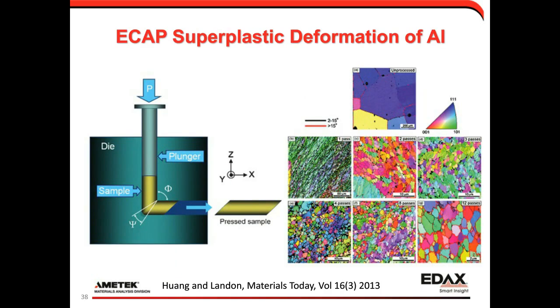And this is just an example here. One of the things research is focused on is using different methods of introducing superplastic deformation to refine and control the grain size. This is what's called equal channel angular pressing or extrusion, where you push a material through a die that takes a strong turn, in this case 90 degrees. Your pressed sample comes out with the same cross-sectional area, but the microstructure can be significantly influenced and varied depending on the number of passes and the route. You can push it through and then turn it 90 degrees and push it through again, and there are different routes that go through that way. This is an example from aluminum from that same Materials Today article.